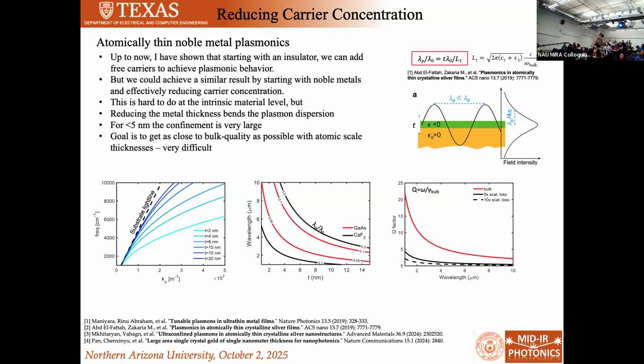By the way, if you do this, what you'll see is your dispersion curve bend away from the light line, which is the characteristic that we showed associated with surface plasmons. Now, the reason why this is quite challenging is because, first of all, it's really hard to make nanometer thickness metal films. If you've ever deposited metal in a thermal evaporator or a sputterer, you know that there's a percolation thickness. You have to get to a certain thickness before you can even hope that it's planar. There are ways to do it. It's just really expensive.